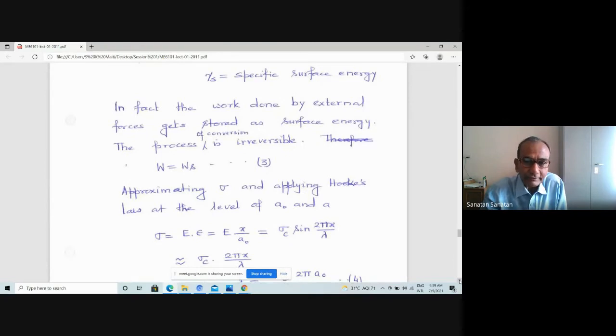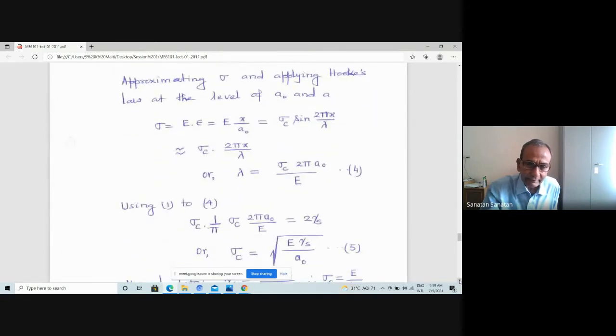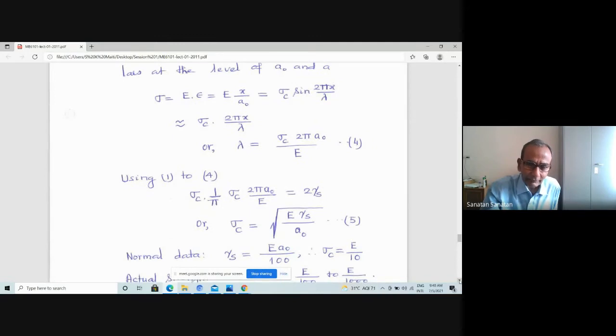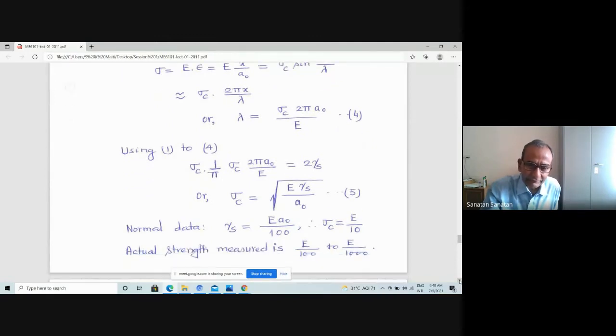So you see that for energy conservation, the work done is equal to surface energy. By making some approximations about sigma as modulus of elasticity multiplied by strain, and doing a little bit of manipulation, if you make use of W equal to WS, finally it gives you the strength, the maximum tension required, calculated as E into gamma S by A0. What is this? E is the modulus of elasticity of the material, gamma S is the specific surface energy per unit area, and A0 is the initial spacing between the two atoms.